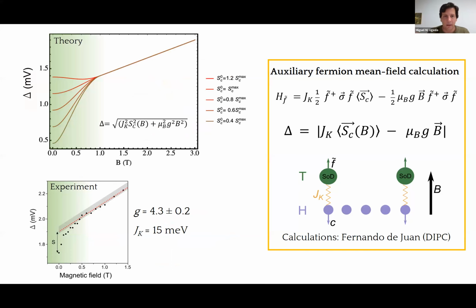But this minimal model can also capture the non-linearities that we observe in the separation of the peaks at low fields. And the reason is because of this first term, in which we take into account the magnetization of the conduction electrons, right? So there are two terms. When the magnetic field is large, this second term dominates, and the system is just linear.